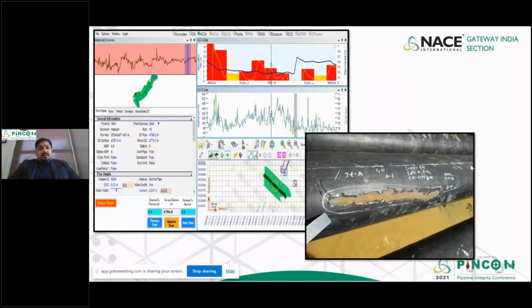But even in this area, we could still see holidays, and something like this was caught. And if you see the attenuation in the area, it's less compared to the coal tar attenuation that we saw earlier, a couple of slides before this. This makes scientific sense as well, because the 3LP coating is in place exactly. It's not degrading like the coal tar coating is. Plus, we know it's new coating, therefore it's not supposed to be losing out on attenuation. But still, there was a holiday which was most probably caused by a third-party defect or something, and which was caught by the program.